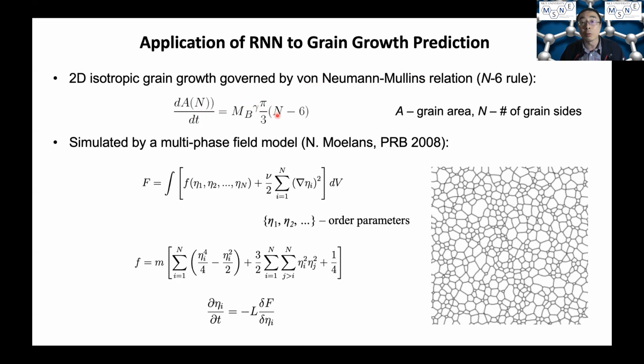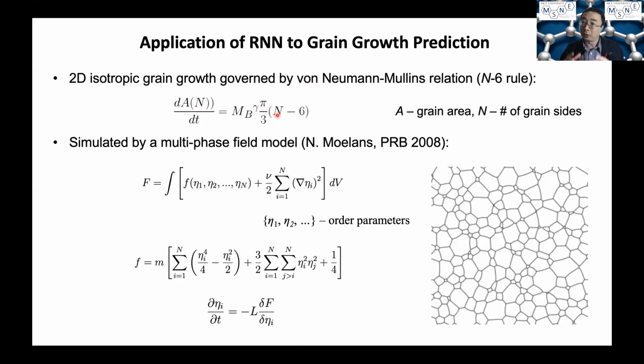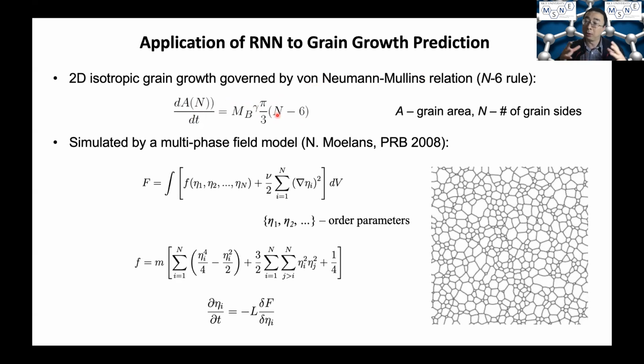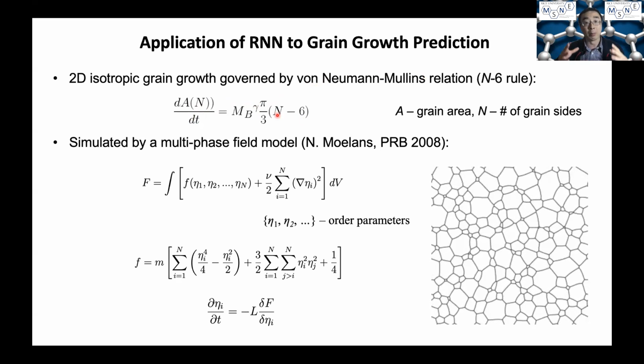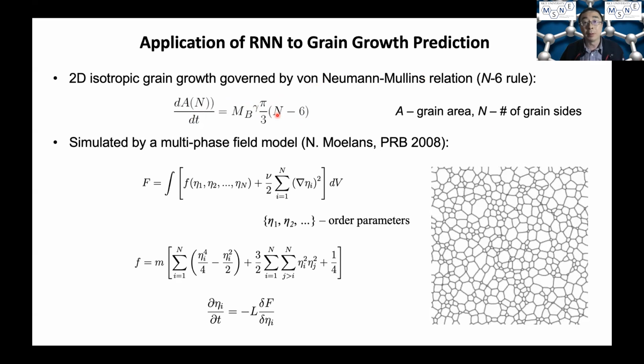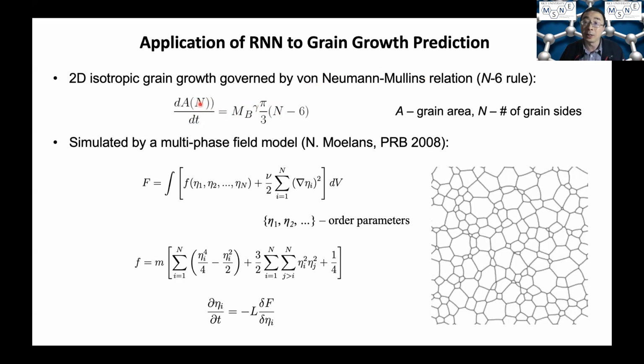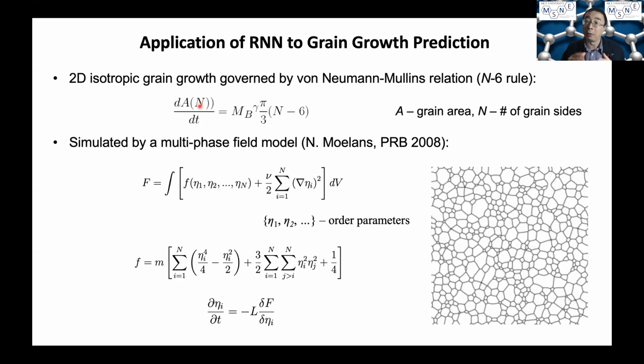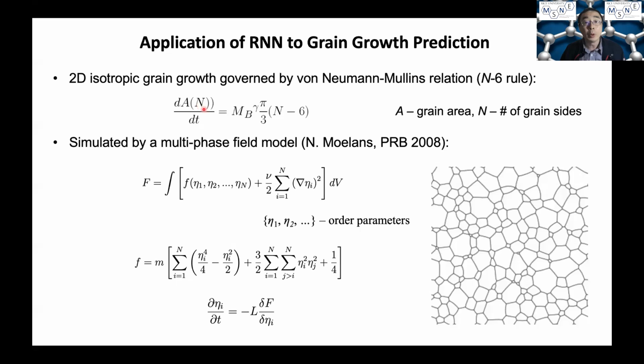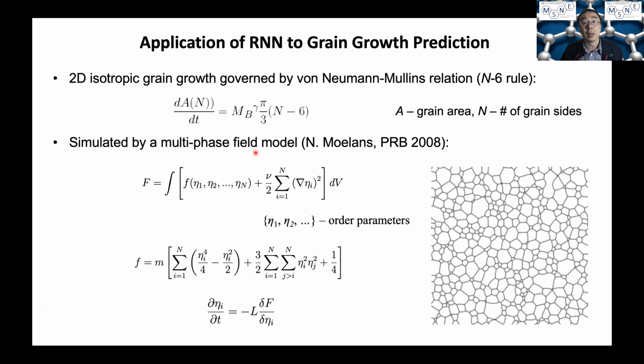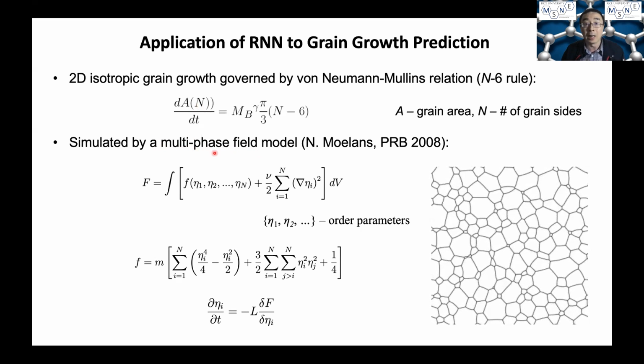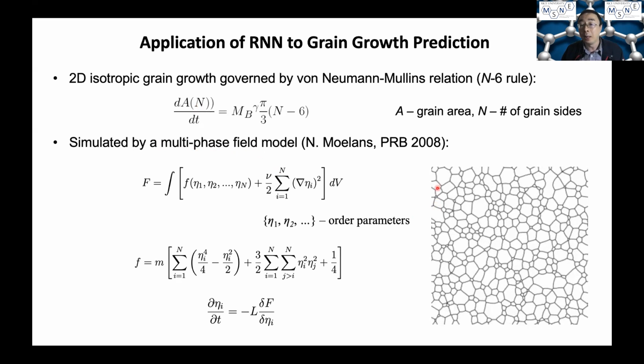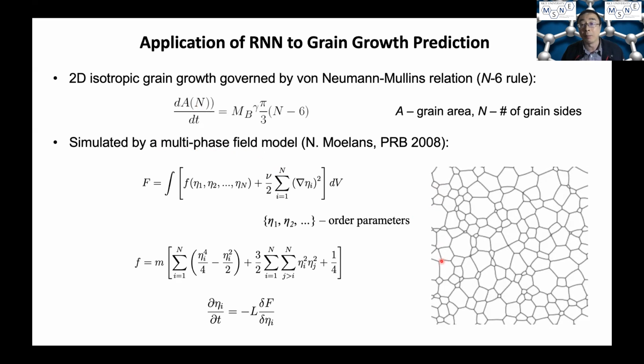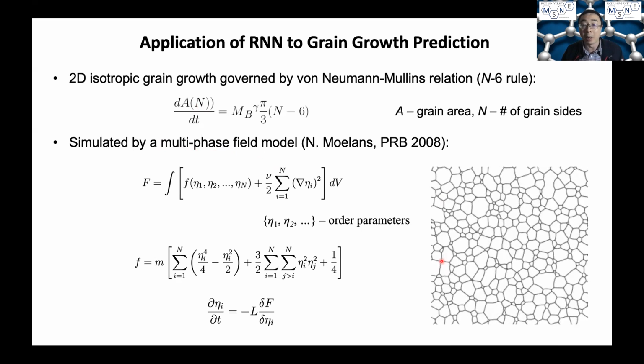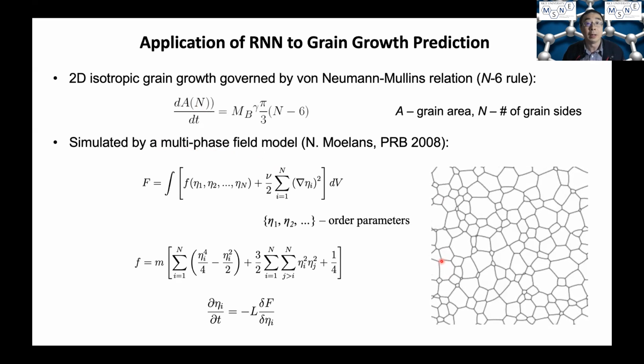When a grain has more than 6 sides, the grain is the lucky one. It will grow at the expense of its neighbors and become larger and larger. But if a grain has fewer than 6 sides, then it will shrink and eventually disappear. And we can simulate the grain growth process using a phase field model. This is how we generate a training data set to train the RNN model for predicting the grain growth process.